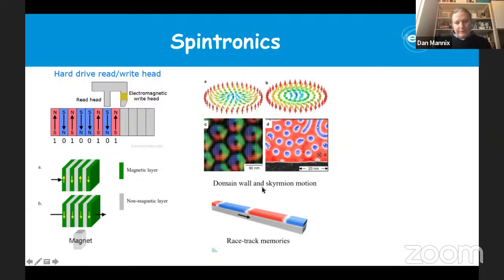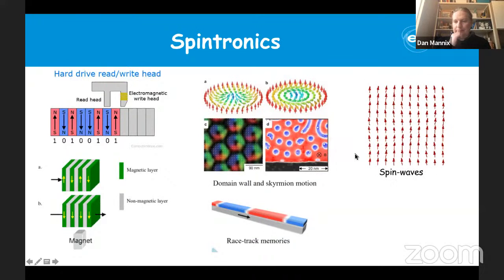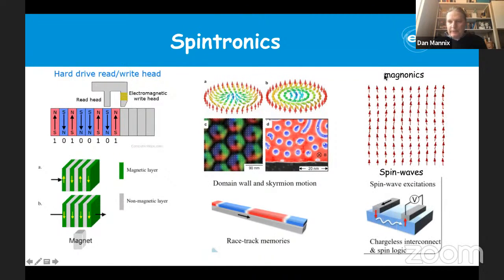Another aspect is domain walls and using domain walls in motion and studying domain walls and these kind of racetrack memories. And another aspect of these materials, Spintronics, originally is using magnons or spin waves, and this is a field which is growing called magnonics, where you can actually use spin waves or magnons basically as information carriers in possible devices. And the advantage there is that using magnons or magnetic excitations uses a lot less energy than moving charges around. So this could be very low power consumption kind of electronics developments if you can use those kind of magnetic excitations rather than magnetic moments themselves or charge moments to move around.